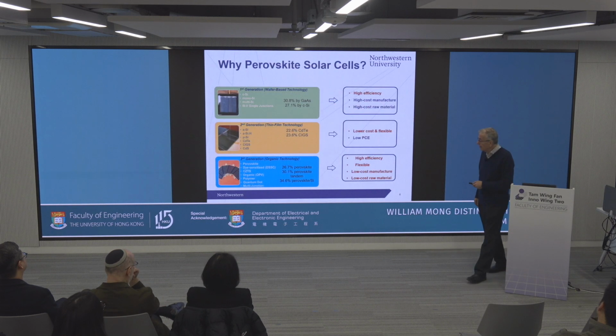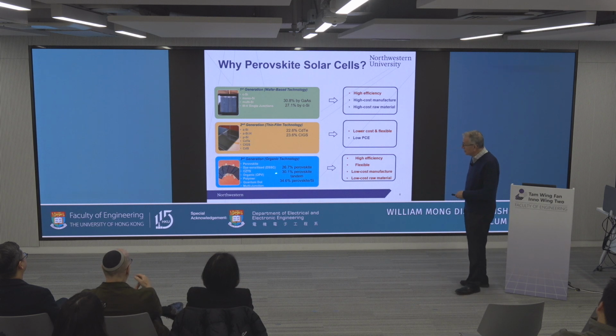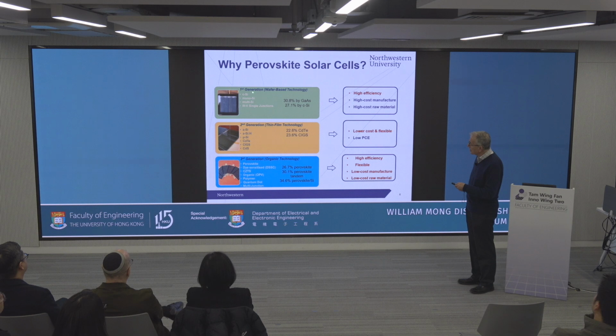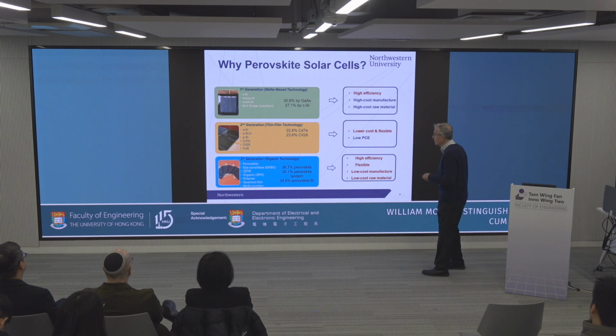So they have joined the third generation photovoltaic technologies. Over time, we had the first generation based on single crystalline materials, gallium arsenide and crystalline silicon, which is, of course, the most commercialized material with very high efficiencies. Then we have the second generation, the polycrystalline film technologies, such as cadmium telluride and copper indium gallium selenide, with very high, also commercialized, at least the cadmium telluride.